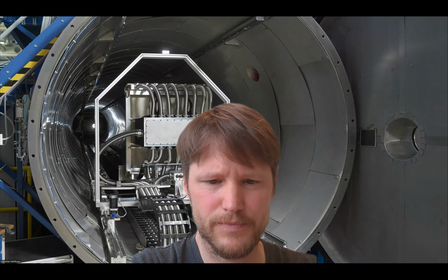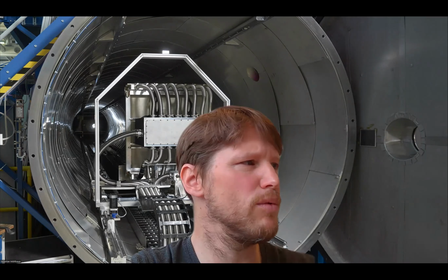Okay, so what do we extract? What we extract is the integrated intensity for every single reflection that we observe. Okay, what else can you extract? Depending on the arrangement of the Bragg reflections, we can also obtain the anisotropy of the vortex lattice, or what we usually know as the opening angle between Bragg reflections. Okie dokie. What else can you be looking at?